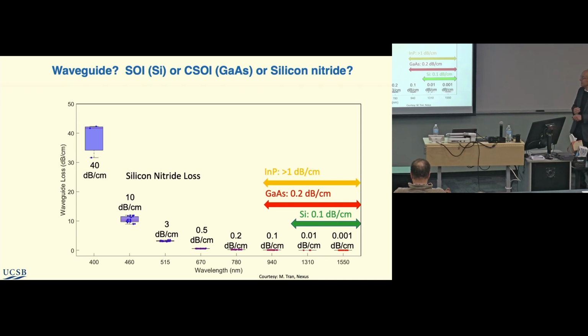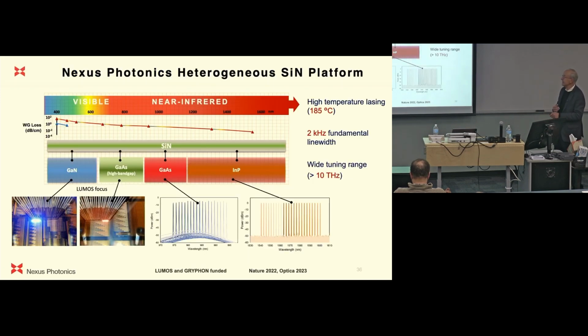So even at 400 nanometers, this is actually much higher—I think now the field is down more like 12 dB per centimeter. But you're getting into that range where silicon nitride and silicon oxide become absorptive in the blue and UV. If you make it with nitride though—this is another spin out of my group, Nexus Photonics—they're trying to make lasers from 1550 into the visible, and you can see a bunch of tunable lasers at a variety of wavelengths.